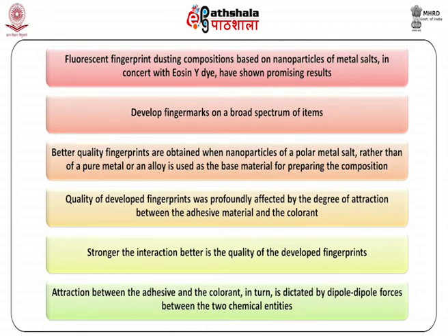Fluorescent fingerprint dusting compositions based on nanoparticles of metal salts in concert with eosin Y dye have shown promising results. These develop finger marks on a broad spectrum of items. It has been observed that better quality fingerprints are obtained when nanoparticles of a polar metal salt rather than of a pure metal or an alloy is used as the base material for preparing the composition.